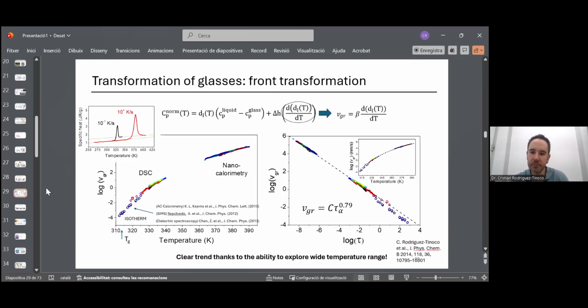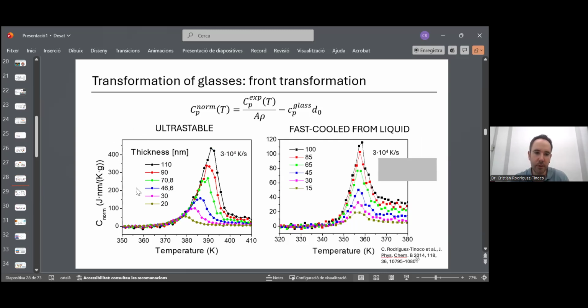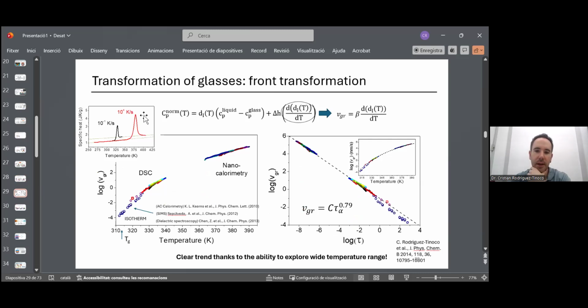So everything works here, and in fact, from this calorimetric curve, we can obtain this growth front velocity. With this term here, the variation of thickness of the liquid phase as a function of temperature can be related to the growth front velocity, the velocity of this front that travels into the bulk, with this expression. And this is what we get with calorimetry, with conventional DSC, and with other techniques. And this is the relationship we get when we plot this against the relaxation time of the liquid. This tau is the relaxation time of the superheated liquid, and it follows this empirical relationship here, which works with this exponent, which should be negative. There's a mistake. This exponent is quite similar in different systems.